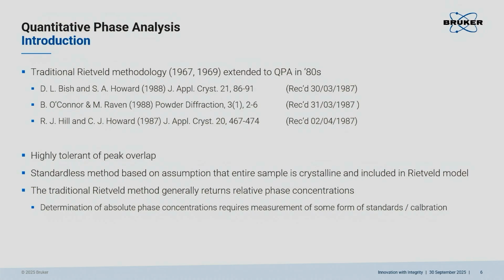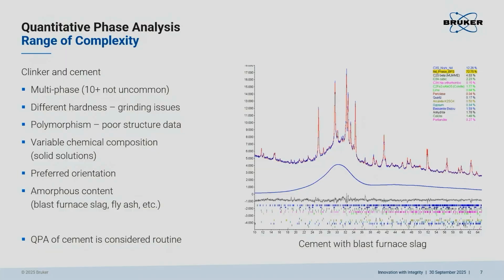It becomes clear if you think about amorphous content, or if you think about phases which you cannot identify or which you simply missed. So in this case, you always have to be aware, by default, using the traditional Rietveld method, you only obtain relative phase abundance.